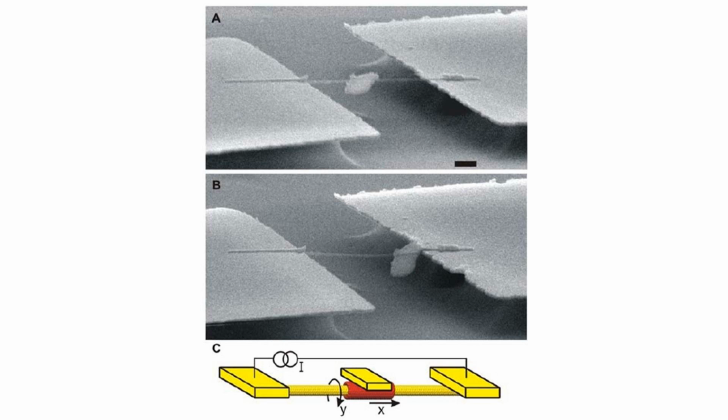Molecular dynamics studies show that, with the exception of small peaks, the frictional force remains almost negligible for all sliding velocities until a special sliding velocity is reached. Simulations relating the sliding velocity, induced rotation, and intershell frictional force to the applied force provide explanations for the low interwall friction. Contrary to macroscale expectations, the speed at which an inner tube travels within an outer tube does not follow a linear relationship with the applied force.